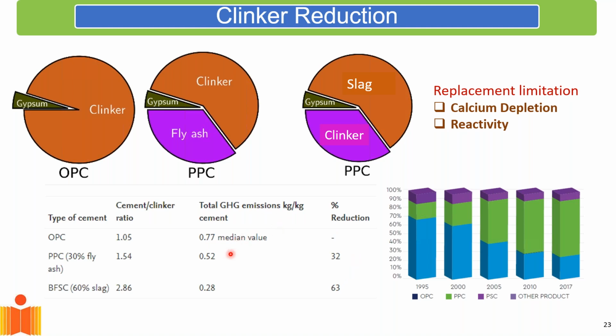If you look at the greenhouse gas emission, then if I look at OPC and start with the 0.77 median value, by the time I come to fly ash, I've dropped down to 0.52, and for blast furnace slag, I drop it down to about 0.28. So there are significant reductions in the greenhouse gas, the carbon tag, the carbon that is associated with the cement.